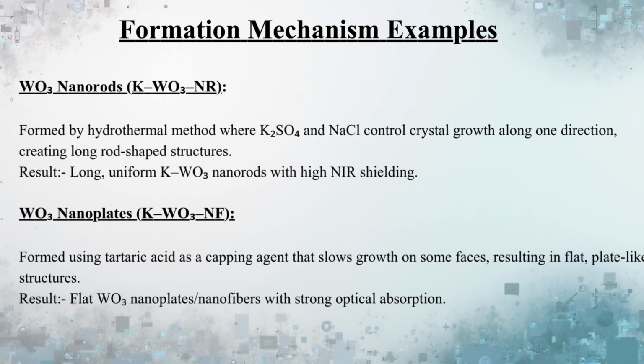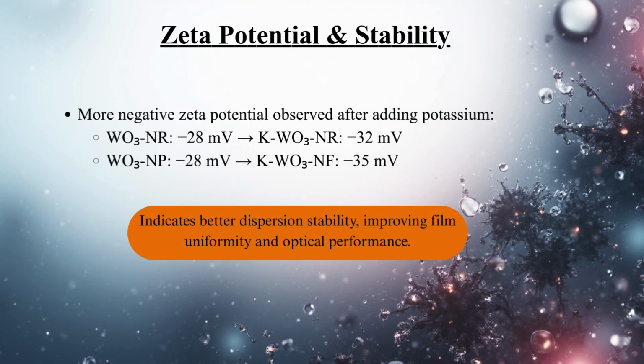Example of formation mechanism. The formation of the two KWO3 shapes: nanorods are grown by agents like NaCl that promote one-dimensional growth, yielding long rods with high NIR shielding. Second, nanoplates or nanofibers are grown by using tartaric acid as a capping agent to block certain faces, yielding flat structures with strong optical absorption.